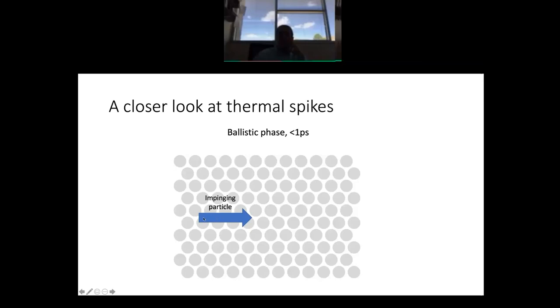So suppose that I have my crystalline solid. Here's an impinging particle. The first thing that happens in a thermal spike is that this impinging particle dissipates its energy to surrounding atoms through some many-body collision process. And each of those atoms then gets a certain energy, right? So all the atoms that I've shown here with red arrows have received a kinetic energy that's above a threshold energy known as the displacement threshold. And this threshold energy depends on the material, and it also depends on the crystallographic direction of the material, but generally is on the order of a few tens of electron volts. So let's say 20 to 80 electron volts.